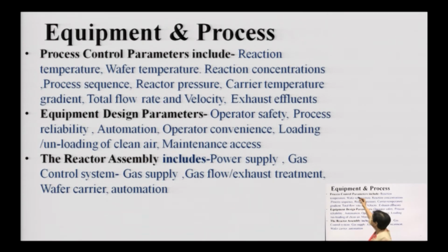Similarly, there are other parameters also. The process control parameters, as I told you, are the reaction temperature, the wafer temperature, the reaction concentration, the sequence in which the wafers are introduced to the chemicals or gases being deposited, and then the pressure and temperature of the carrier which is introducing those dopants or depositing species onto the wafer.